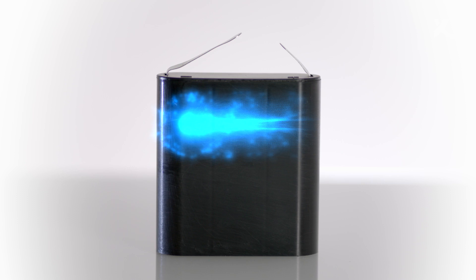When you make a battery, it consists of a cathode and an anode. The anode is typically graphite — the same graphite you have in a pencil. When you charge your battery, the lithium ions go from the cathode to the anode. If you're charging too fast, you can't get the lithium ions in between the layers of carbon — the graphite layers — and instead you get lithium deposits that form on the carbon, creating filaments and fibres. If they grow too large, they connect the anode to the cathode and short-circuit the battery. When you get a short circuit, the battery discharges very fast, it heats up, and that's when you get fires and explosions — one of the key failure mechanisms of a lithium-ion battery.